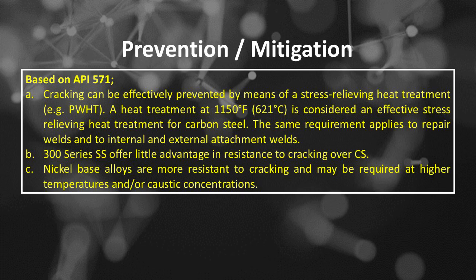Caustic embrittlement prevention and mitigation based on API 571. Number A, cracking can be effectively prevented by means of a stress-relieving heat treatment, such as PWHT. A heat treatment at 1150 degrees Fahrenheit or 621 degrees Celsius is considered an effective stress-relieving heat treatment for carbon steel. The same requirement applies to repair welds and to internal and external attachment welds. Number B, 300 series SS offer little advantage in resistance to cracking over CS. Number C, nickel-base alloys are more resistant to cracking and may be required at higher temperatures and/or caustic concentrations.